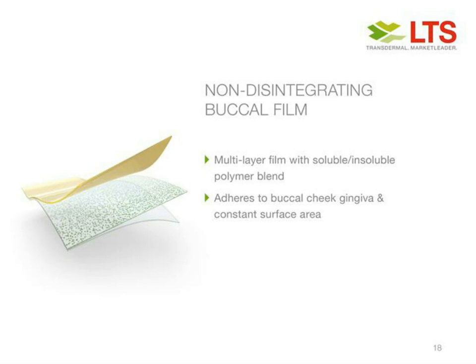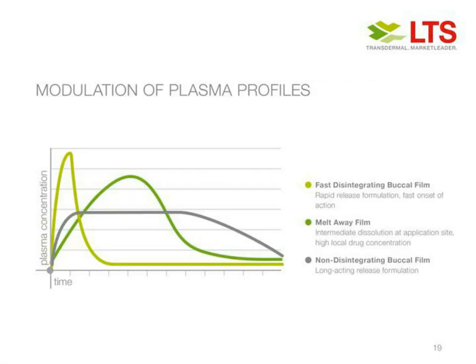So if you look at the absorption kinetics, and this is obviously a graphical representation, and it varies a little bit depending on the type of API. With a fast disintegrating buccal film, you typically have a very, very early spike of the peak, and then it falls off. Melt away, as I said, is more the typical profile, and instead of your T-max being 1 to 2 hours, sometimes it offers the opportunity of reducing that T-max. The non-disintegrating buccal film is typically used very much as a controlled release formulation, and depending on the structure, you may be able to get a rapid onset and then a constant release of the API through the buccal membrane.